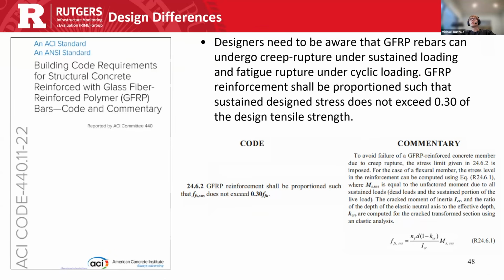Also something to consider is creep rupture under sustained loading and fatigue rupture under cyclical loading. GFRP reinforcement shall be proportioned so that the sustained design stress does not exceed 0.3 of the design strength. And this is outlined in ACI code 440.11.